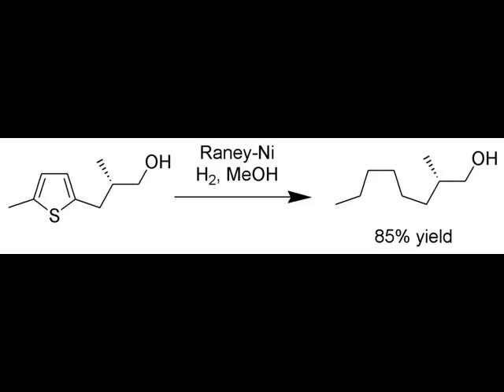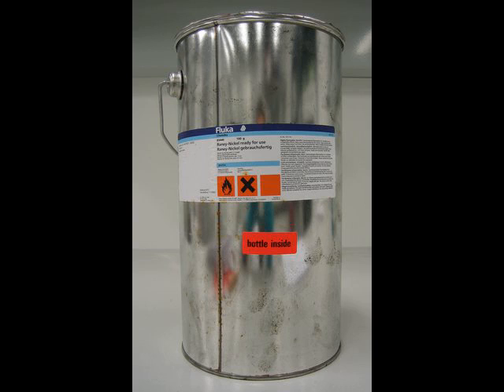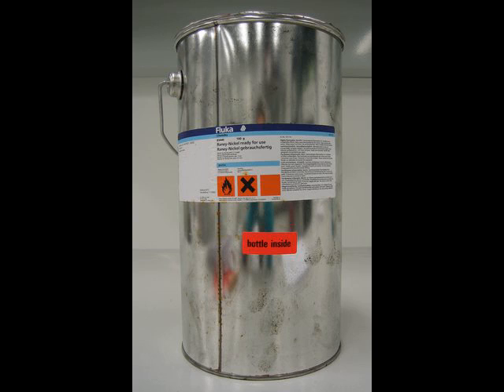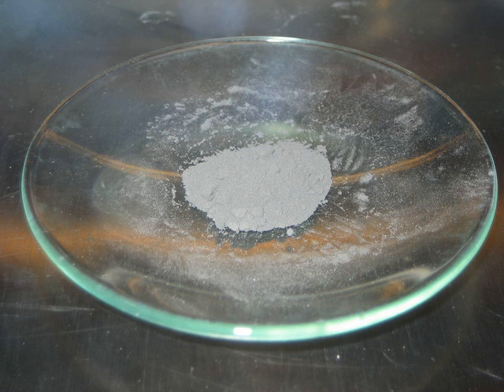The surface area is typically determined via a BET measurement using a gas that will be preferentially adsorbed on a metallic surface, such as hydrogen. Using this type of measurement, it has been shown that almost all of the exposed area in a particle of the catalyst has nickel on its surface. Since nickel is the active metal of the catalyst, a large nickel surface area implies that there is a large surface area available for reactions to occur simultaneously, which is reflected in an increased catalytic rate. Commercially available Raney Nickel has an average nickel surface area of 100 m² per gram of catalyst. High catalytic activity, coupled with the fact that hydrogen is absorbed within the pores of the catalyst during activation, makes Raney Nickel a useful catalyst for many hydrogenation reactions.